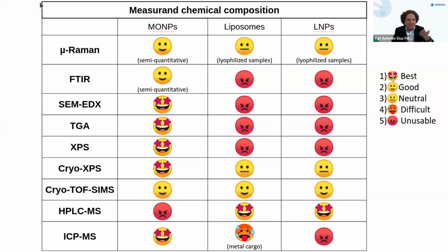And it's something similar to FTIR, with the difficulty that in the case of Raman, you can do micro analysis. In the case of FTIR, unless you have a micro FTIR, an instrument that exists although it's not so common, generally you will use an ATR FTIR, and you will need a little bit more material, and you cannot go to the micrometer scale, let's say.